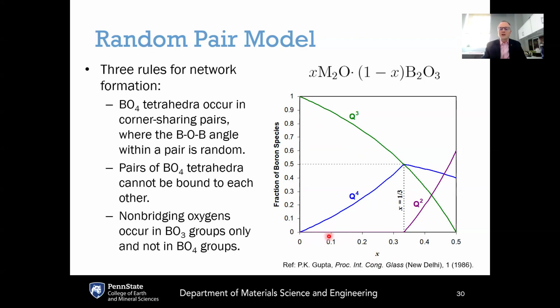As you increase the modifier content here, X, initially borons convert from trigonal to tetrahedral coordination. This increases the connectivity of the network, and this continues until you get to this 1/3 concentration of modifiers where the population of Q4 units is equal to the population of Q3 units. At this point, it's not possible to form additional Q4 units and still satisfy this rule that pairs of BO4 tetrahedra cannot be bound to each other.